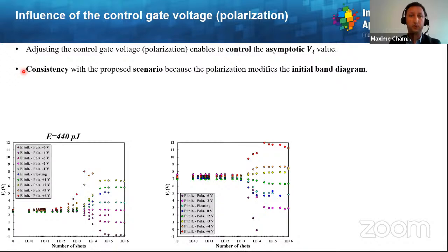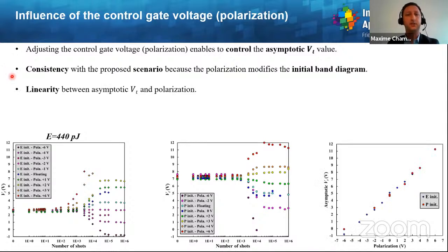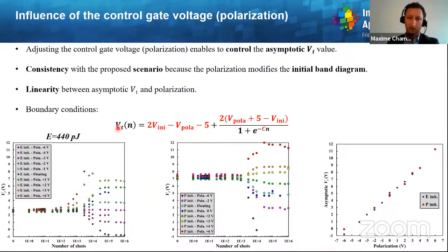This is consistent with the proposed scenario because the polarization will modify the initial band diagram. And we also observe the linearity between the threshold voltage and the applied bias. This allows us to determine A and B in the sigmoid curves, so two of the 3 free parameters, which are related to the boundary conditions. So now we just need to evaluate what C is and how it can be related to the laser parameters.